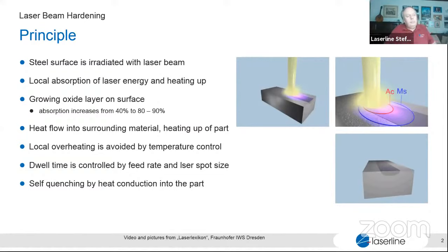Anyway, if I speak about hardening, it is a heating process, first step, to a certain level of temperature, depending on the material. And then we have a quenching. And the quenching happens, in that case, by heat flow into the cold part of the whole part. So we make just the surface heating and then heat flows rapidly into the complete volume of the part. And this is the most effective quenching that you can have. So it's better than any liquid quenching with Leidenfrost phenomena and anything.